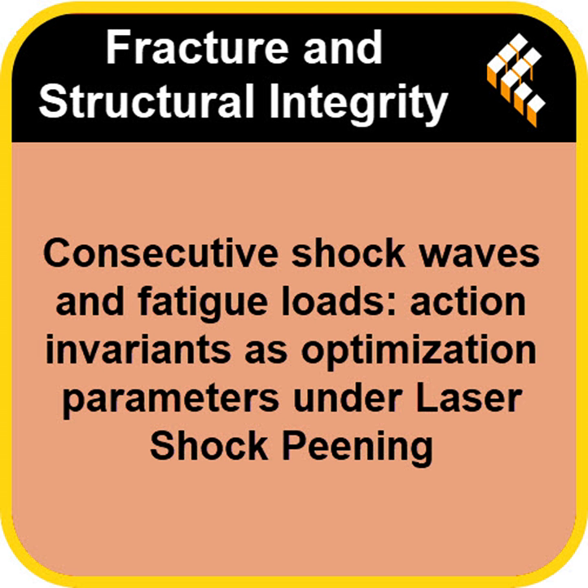There's a corresponding fatigue action invariant, A_F, which is related to the total time it takes for the crack to propagate to failure, T. And that shared exponent of 4 connects A_LSP, from the initial shock treatment, to A_F, the ultimate fatigue life. That's the core idea. It provides a physical bridge between the treatment and the outcome.